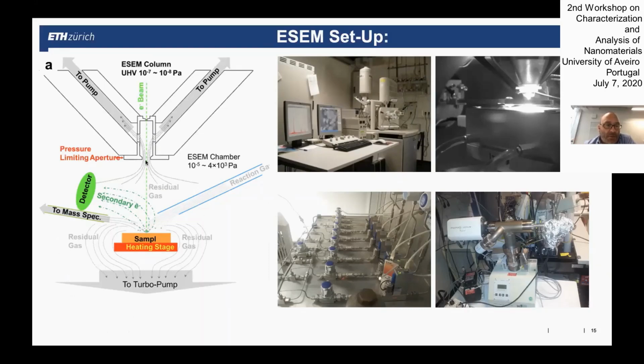We have actually played with these pressure limiting apertures, and we did experiments up to 1 bar in pressure. So this is really crazy. In principle, during the experiment, you could open the door and just see if everything is looking well. You would probably get exposed to some X-rays, but you can really work in a very large pressure range. The gas is introduced at some place, either locally feeding directly onto the sample or introduced into the chamber. And then we also have a sniffer that goes to the mass spectrometer just to see what's going on.